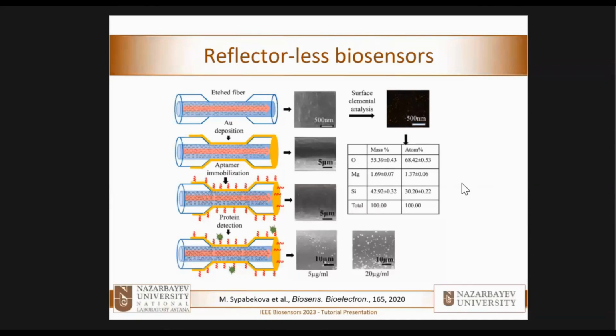The main problem is that when you have a fiber that is very sensitive, and therefore very responsive to the surrounding environment, you also have high losses. So you need to tolerate high losses. The problem is that single mode fibers are engineered to have extremely low losses, so they scatter very little.